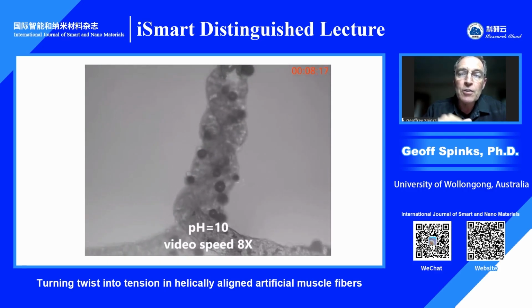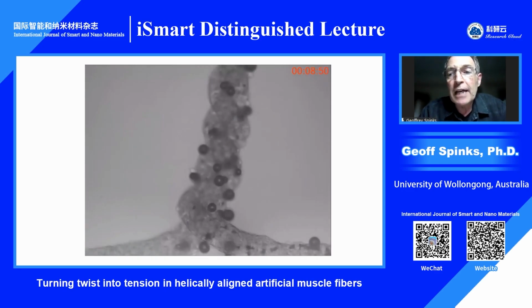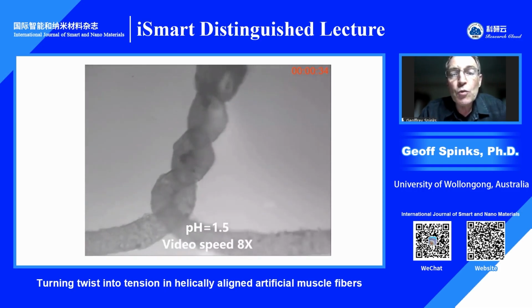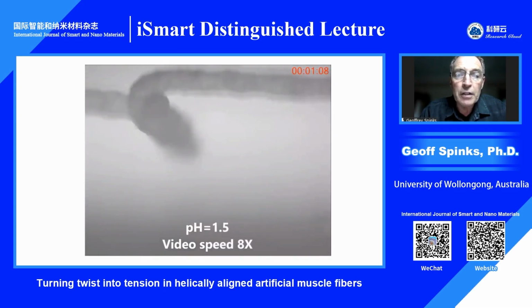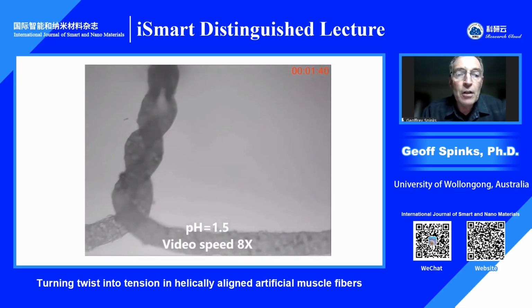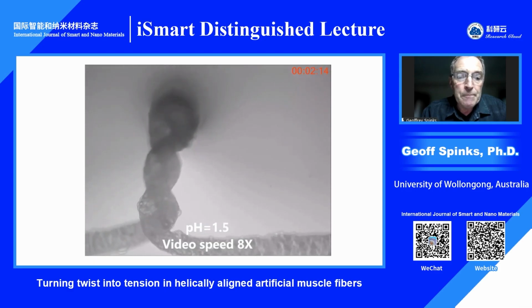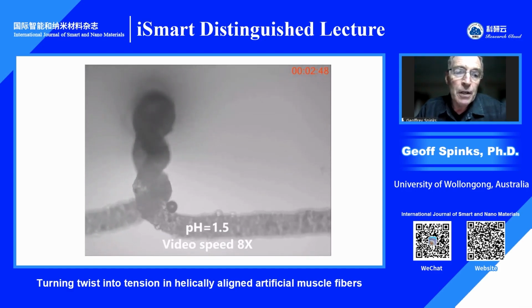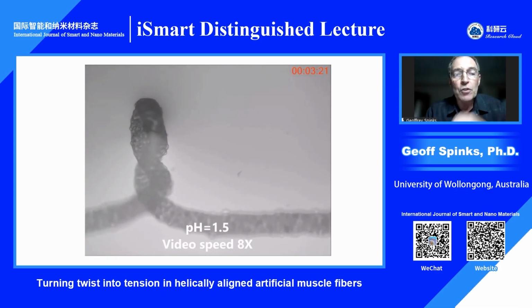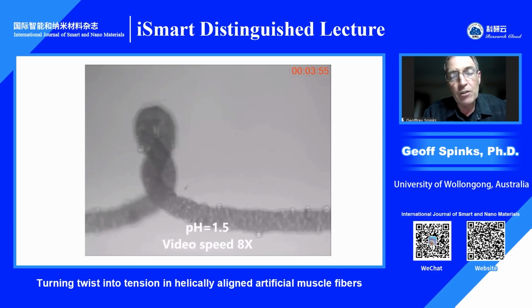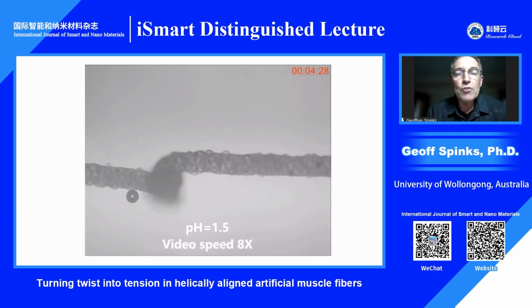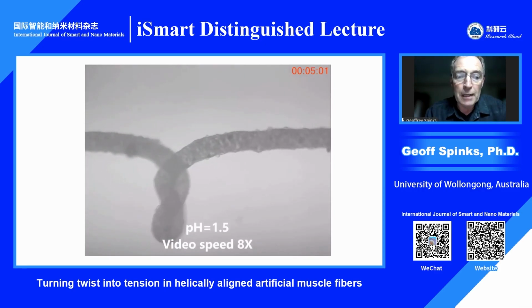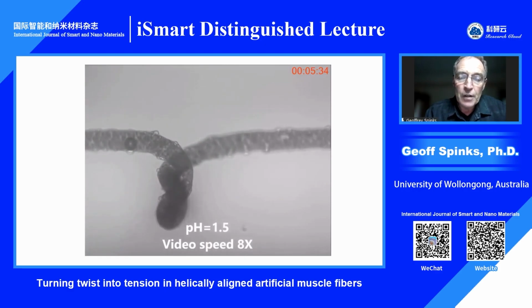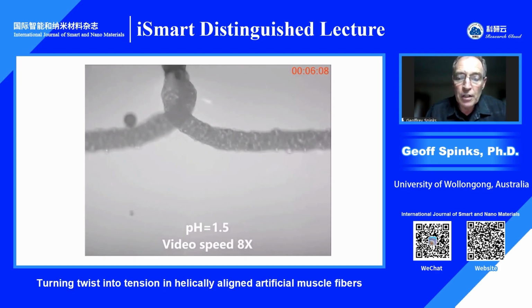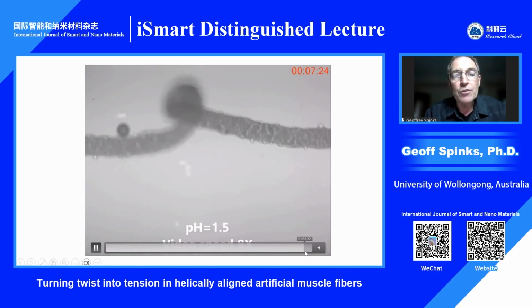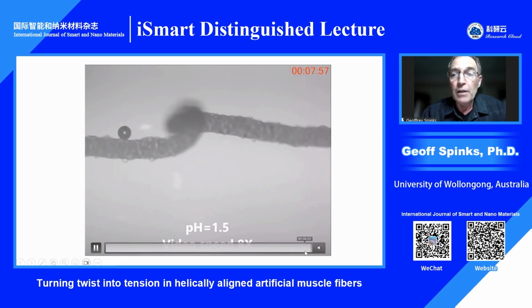For every turn that's produced in the loop, one twist is taken out of the fiber. This is called twist to writhe interconversion, and it's very well known in biology. If the ends are fixed, then there's a relationship called the linking number relationship that shows that the change in twist has to equal the change in writhe of the system, a constant linking number. Now, writhe is quite closely related to out of plane bending of the fiber and can be quantified. So here we're seeing a deswelling in the acid solution, and as you'll see, it eventually goes back to the single coil loop. So this was very exciting.